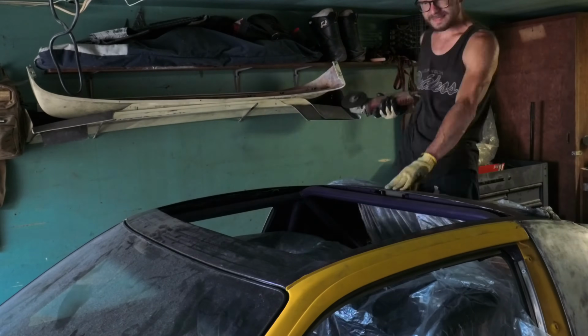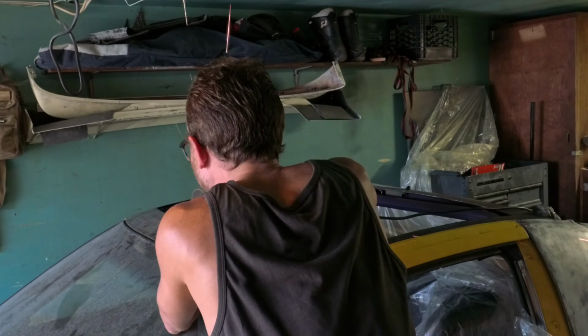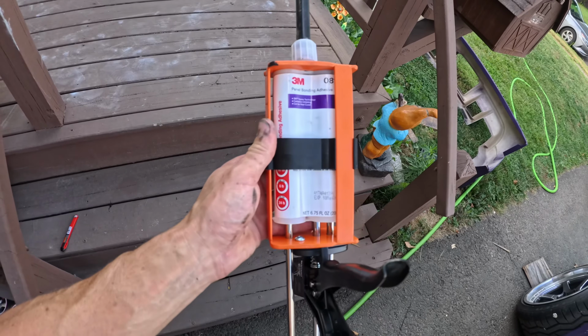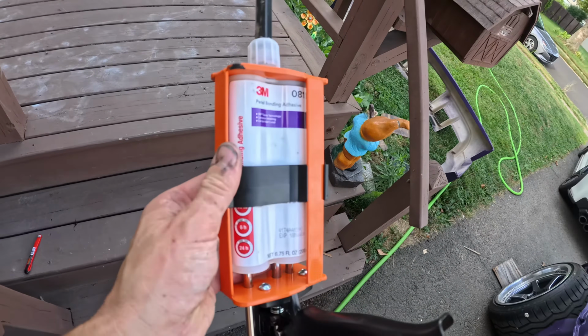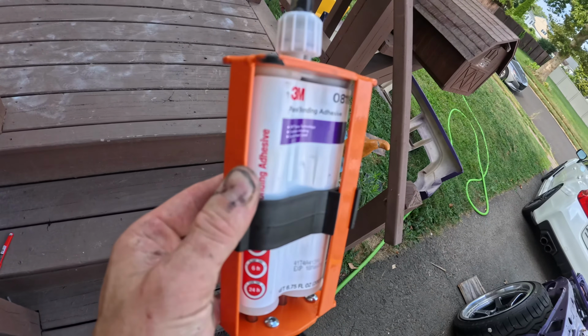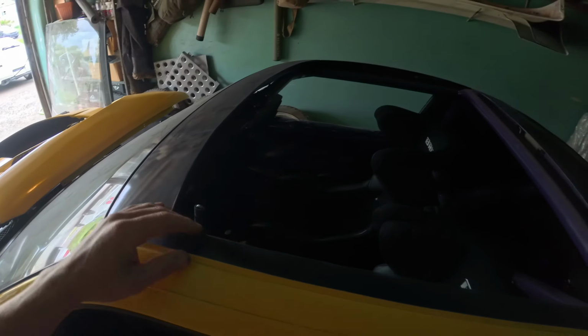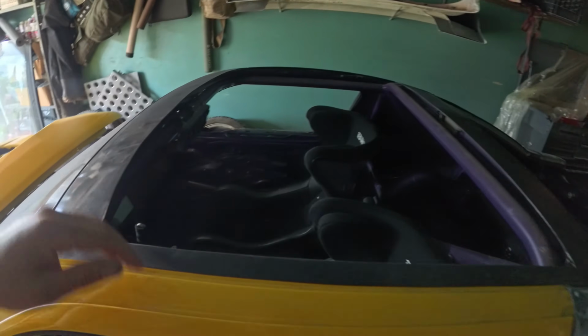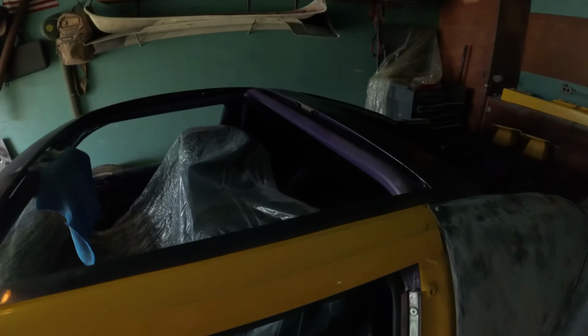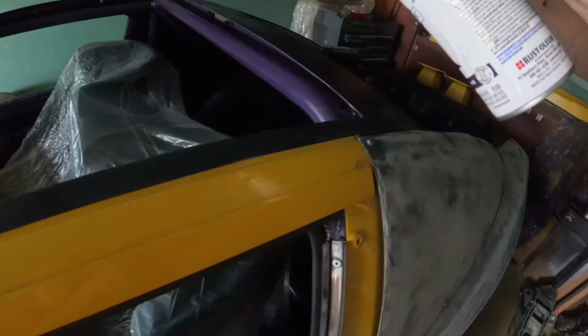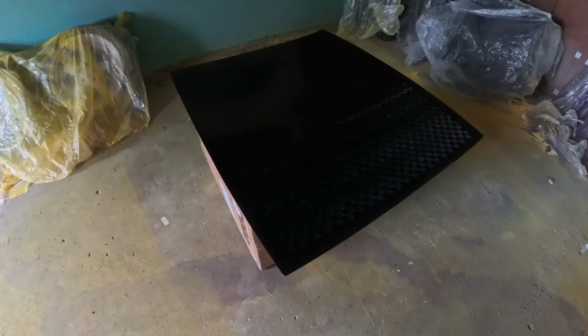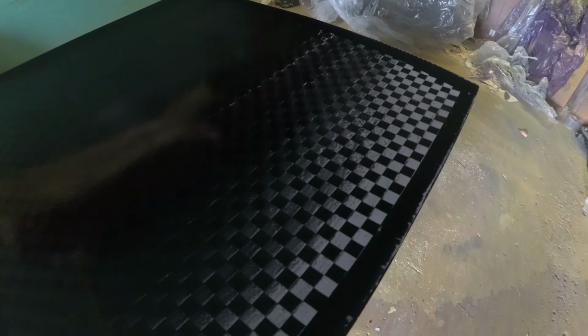Using a flap disc, I deburred the edges and made sure my lines were straight. The 3M panel bond that I'm using requires you remove the paint from the metal panel you are bonding to. Using a flap disc, I removed paint around the border of the roof. I then touched up any bare metal with the same purple paint the interior is painted with to prevent any future rusting. After doing a final fit and trim of the panel, we are ready to hit the inside layer,